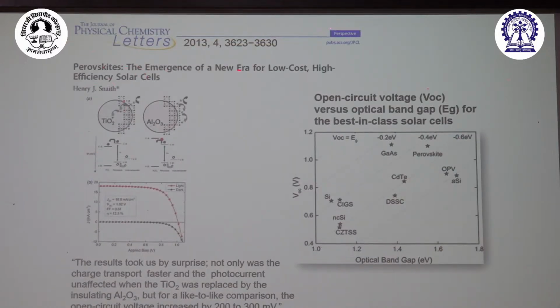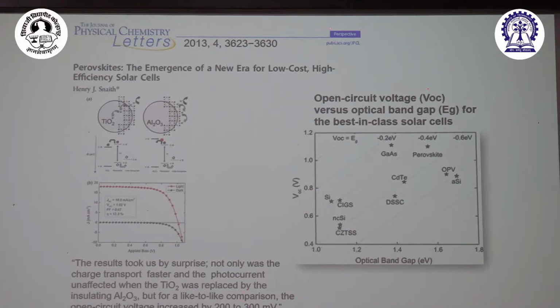And they came back, again, a new era. This was published in 2013. The results took us by surprise. Not only was the charge transport faster and the photocurrent unaffected when the TiO2 was replaced by the alumina, but for a like-to-like comparison, the open circuit voltage increased by 200 millivolts. So again, that's Henry Snaith, he put it. Again, these are the open circuit voltages for different semiconductors, and this is the optical band gap. And as you can see here, these are the different lines, and the perovskite is way up on the top. That means your voltage loss is much less in this material.